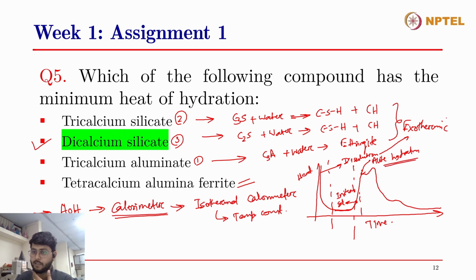अब alite hydration peak के बाद gypsum जाके CSH में absorb हो जाएगा, there will be gypsum depletion in the system, and finally this gypsum will be dissolving from the CSH, ये जाके dissolve हो जाएगा, and then there will be an aluminate hydration peak. So this second peak corresponds with the aluminate hydration peak, and finally it decelerates, and there will be a very small hump at a later stage, somewhat around 14 to 15 hours, and this corresponds with the AFM peak.